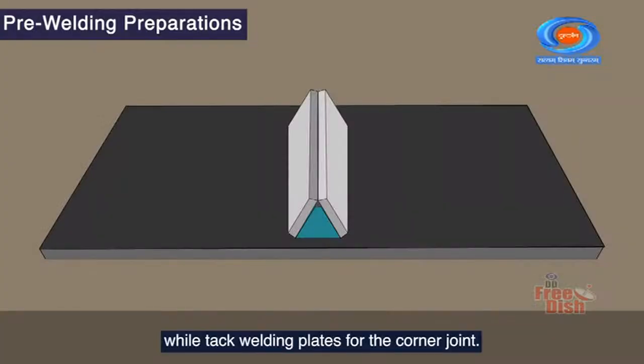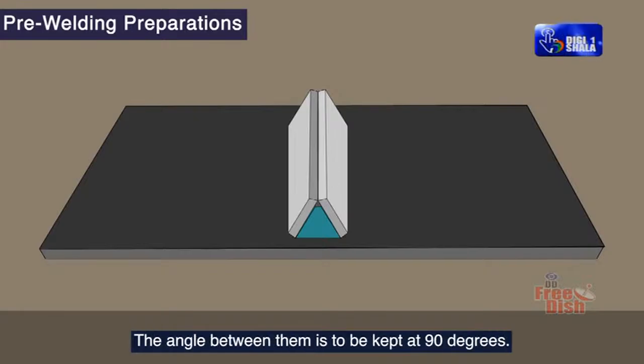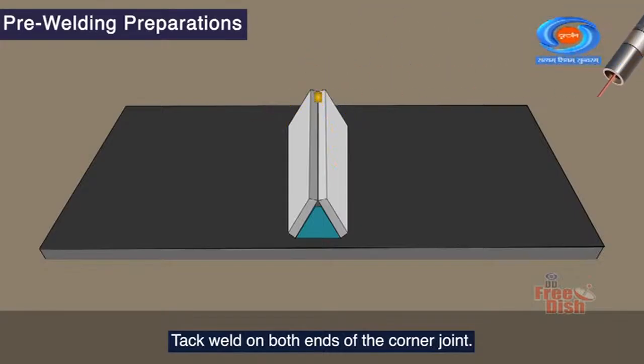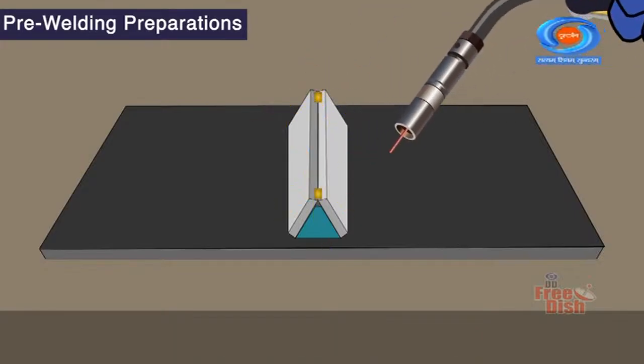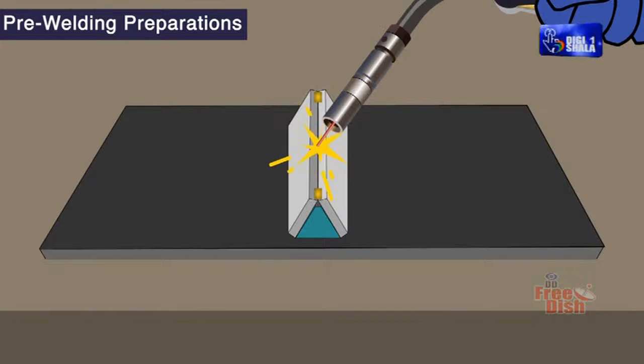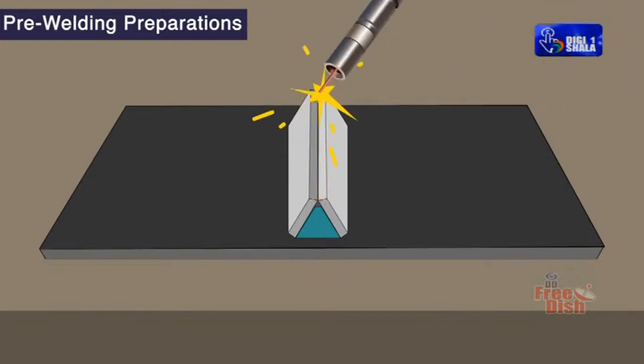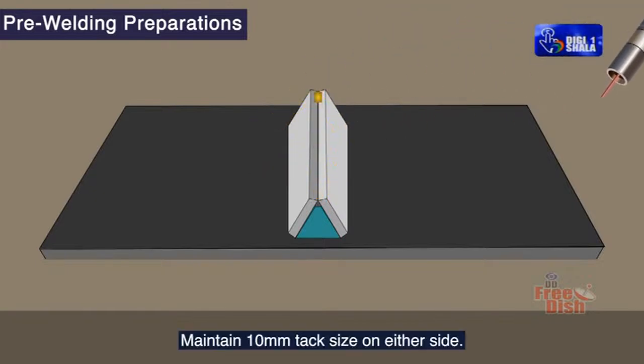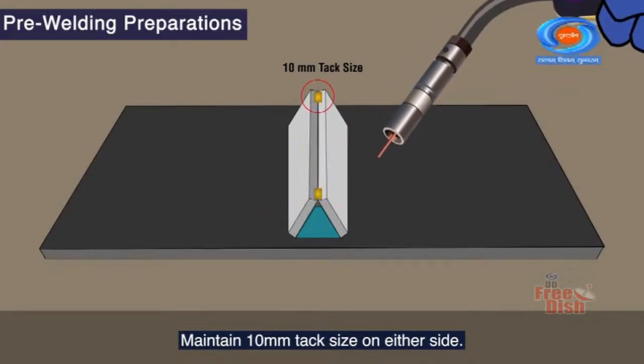While tack welding plates for the corner joint, the angle between them is to be kept at 90 degrees. Tack weld on both ends of the corner joint. Maintain 10 mm tack size on either side.